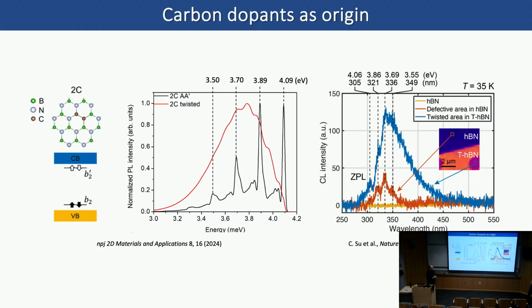We recently have a collaboration with Zhang Miao from UCLA. He did ptychography, multi-slice ptychography, which allows you to go through the focus. So it goes through the sample in depth to show it layer by layer with a depth resolution of 2.5 nanometer. But 2.5 nanometer still has almost 7 to 8 layers of hBN, so you still don't really know what the structure looks like. So the advantage of having everything appear on a monolayer is that you could correlate what the atomic structure of those defects is.